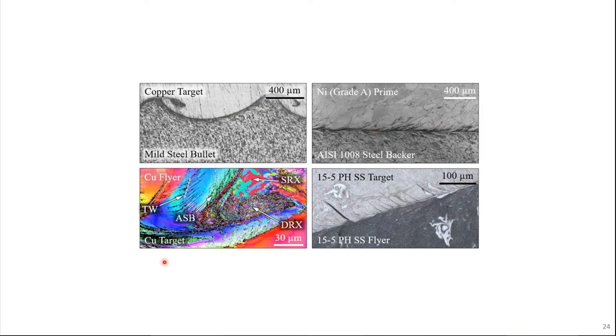In this image you see over here, this was an EBSD image with IPF mapping. You notice all these different effects, like a twin plane forming, adiabatic shear bands, dynamic recrystallization, static recrystallization. This is very interesting. The reason we see all of this is because the material being used over here was copper. Copper has a very low stacking fault energy, and because of that, you get all these exciting effects during that impact weld formation. So this was a very nice picture where all of these phenomena were captured in this one frame. And it was by a group, I believe in Ohio State. This was Glenn Daehn. Glenn Daehn's a leading researcher in laser impact welding, if you want to read about it, from Ohio State. So this was a picture from one of his students' dissertations.